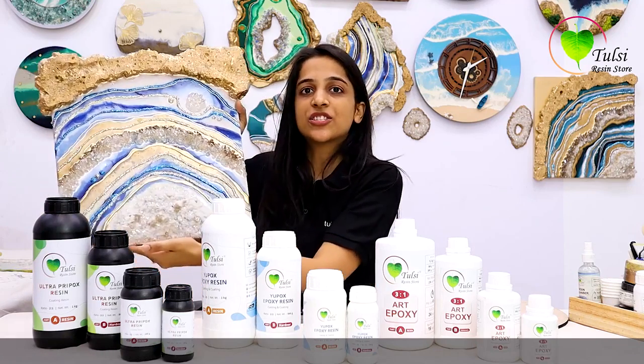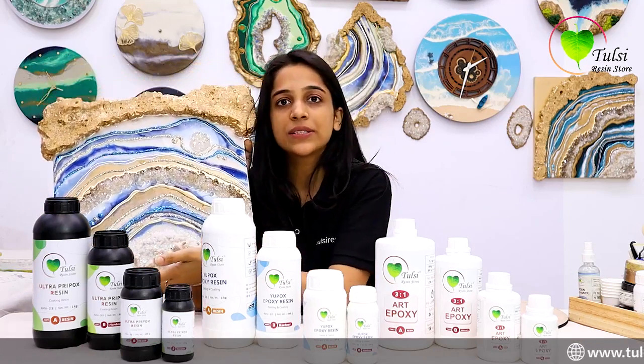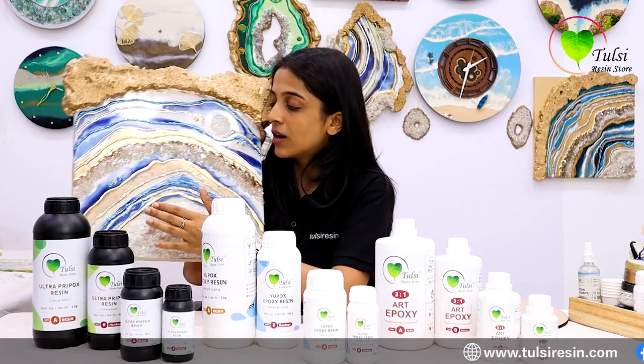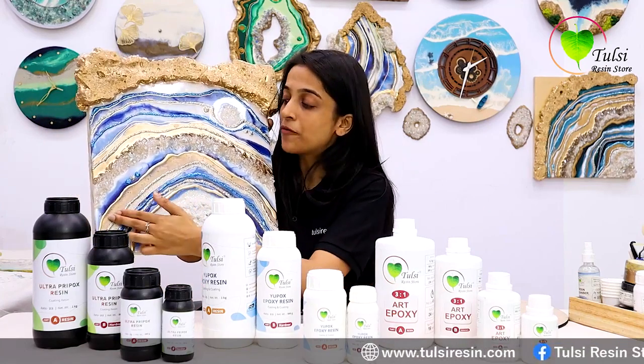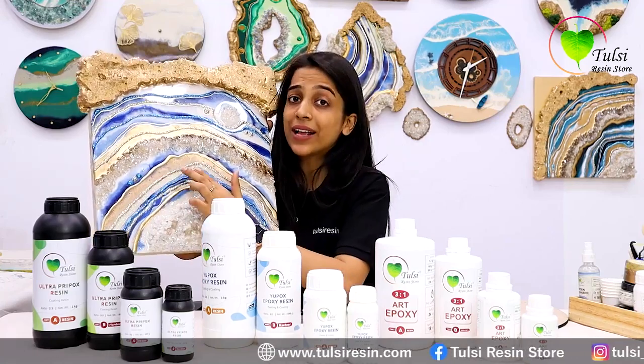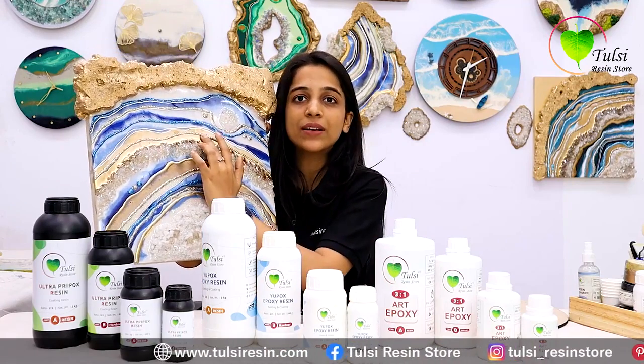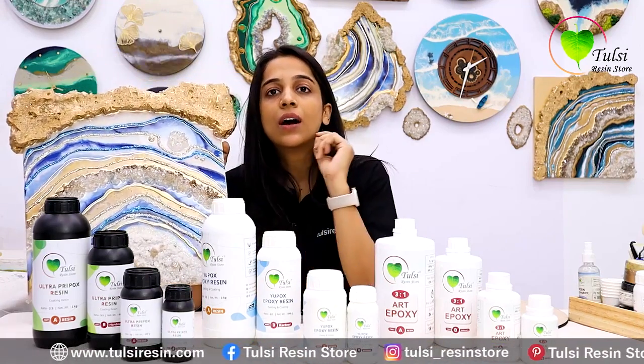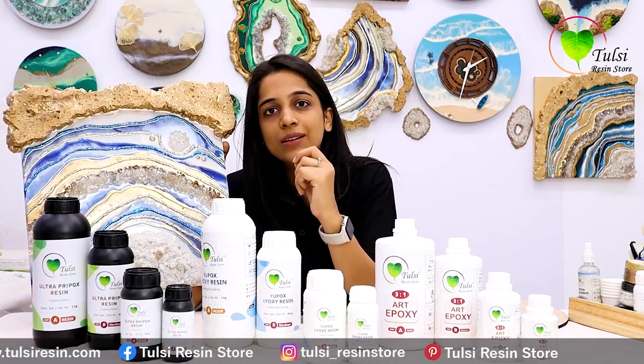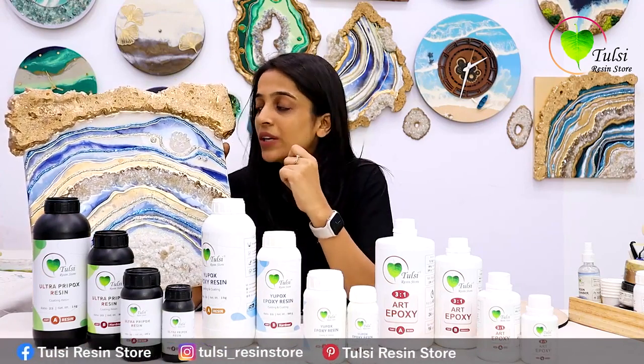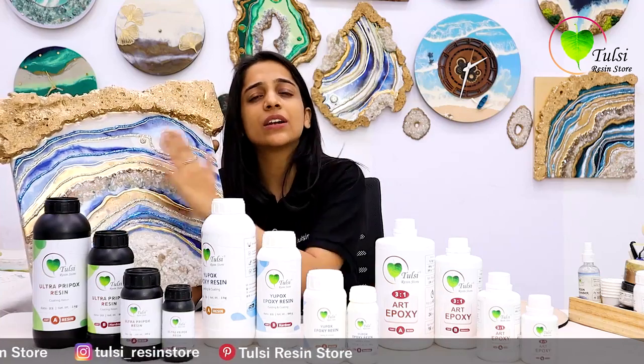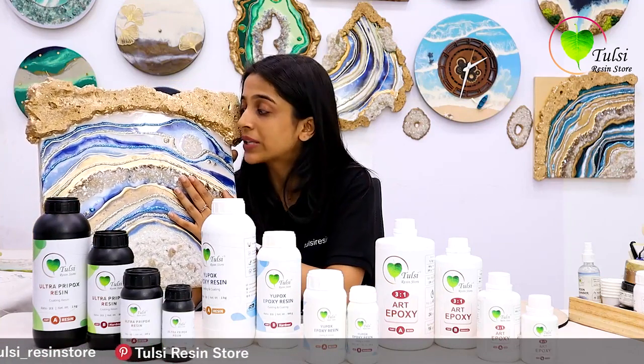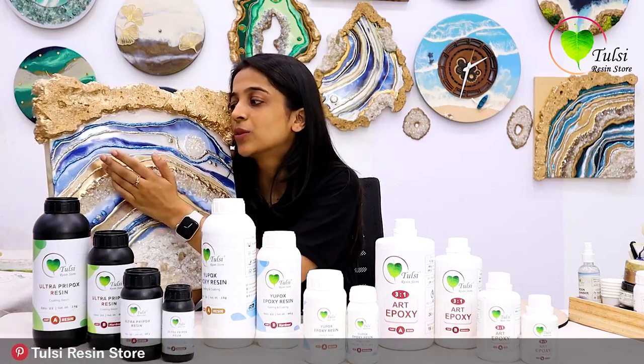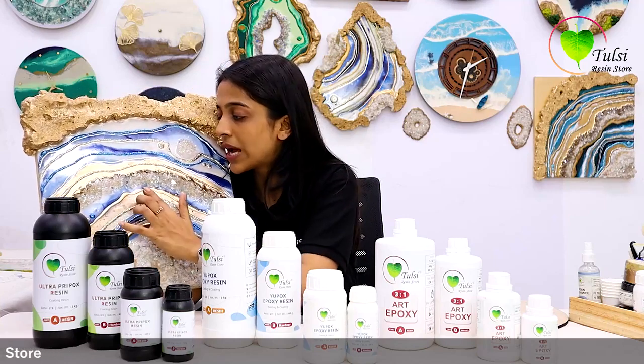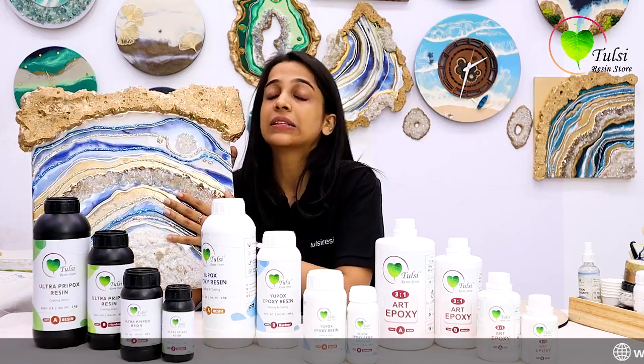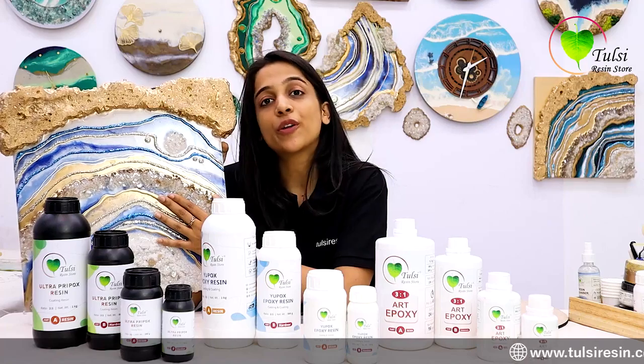As you can see, such pieces, for these pieces you need perfect measurements of resin, perfect thickness to get the perfect lines, glitter lines, perfect pattern, and you need a certain viscosity which is very thick like your sugar syrup. So that's the viscosity of this resin, and it's perfect for geode artworks. You get the perfect lines of glitters, your perfect lines of the golden line and the base line, and this is a very shiny resin for your geode artworks.